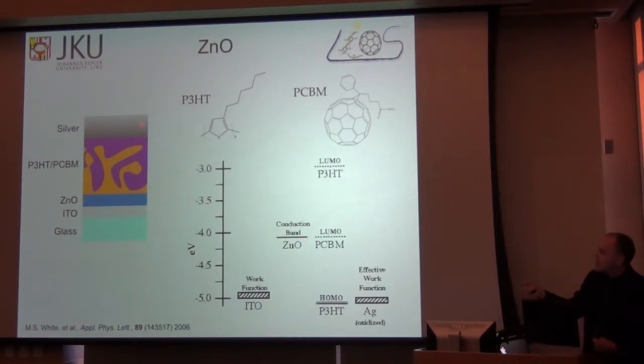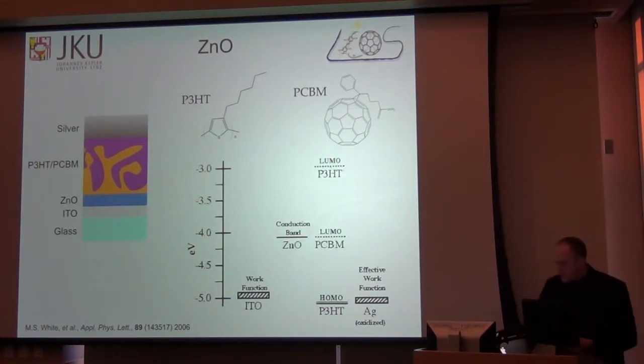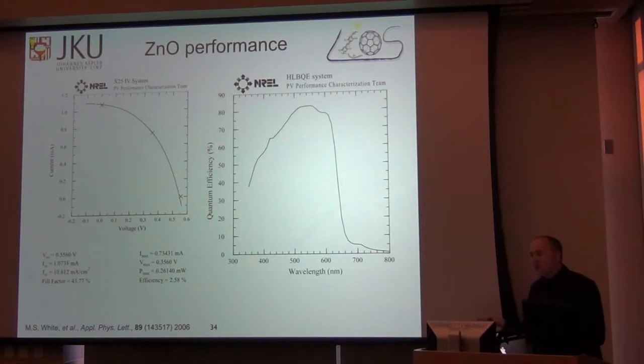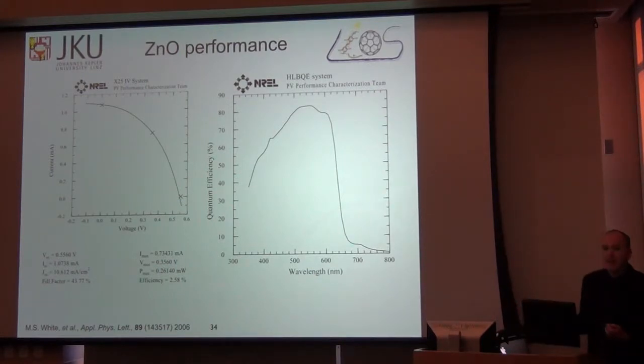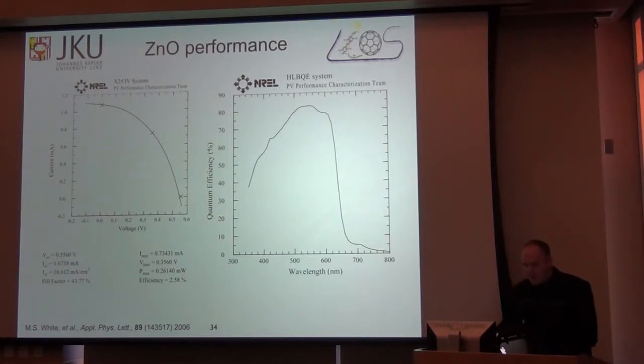And so this device, back in 2005, we made the devices and reported in 2006, produced a 2.5 to 3% power conversion efficiency solar cell, which is at the time state of the art. And it was a completely different device architecture using the same active layers. And so this kind of spawned a revolution in terms of finding different device contact layers that improve the stability. So here we see that the device works on par with what previous devices had.